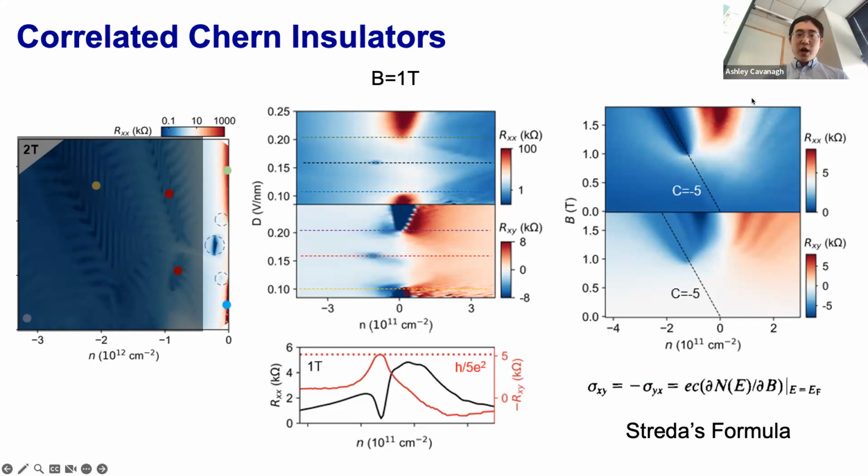Well, all other states, these features are so weak at the same magnetic field, so we think this state of C equals -5 should be thought of as a Chern insulator state that's more robust than the integer quantum Hall. And of course, this state doesn't persist to 0 yet, so it's not a quantum anomalous Hall yet, but we have some thought about what is going on, and how to probably make it more stabilized at an even lower magnetic field. So clearly there's some competing state. When the magnetic field is too small, this C equals -5 is not the ground state to be chosen.